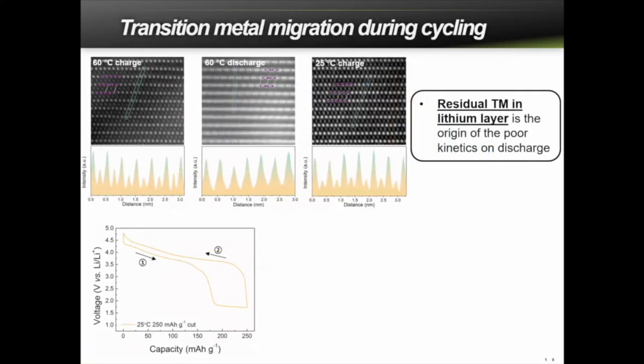From the series of investigations, we found that this asymmetric behavior is coupled with the out-of-plane transition metal migration in the layered structure. So this is the atomistic picture of the layered structure, where the bright spots are the transition metal and the dark layers are lithium layers. And at 60 degrees C, it was found that with charging, a significant amount of transition metal ions migrate to the lithium layer, which is supposed to be completely black, but the presence of this bright spot means that transition metal are occupying this layer. But they reversibly migrate back to the original layer after the discharge, recovering the perfect layered structure.